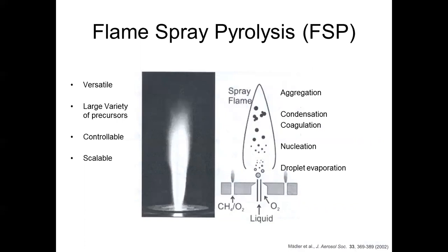Within the burn time, the droplets evaporate and become chemically active. They nucleate and then coagulate into very small, dense particles, because they have a lot of energy at that point. Later in the flame, towards the top, we get more agglomeration, where the particles are loosely linked together.